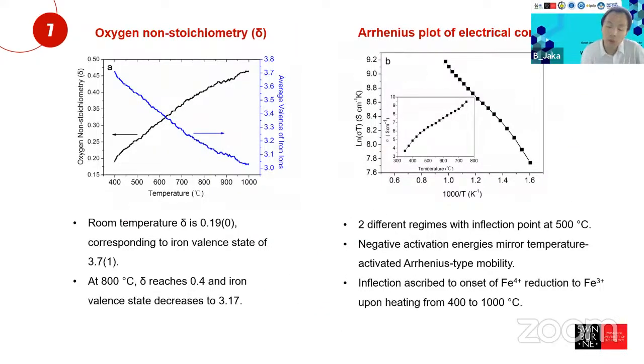So we need to check what the variation of this oxygen non-stoichiometry is at different temperatures. As we go from 400 to 1000, we can see that the oxygen non-stoichiometry increases from 0.2 to 0.45, and this is related to the reduction of the iron oxide in the perovskite lattice in the B site. So as the oxygen non-stoichiometry increases from 0.2 to 0.45, the oxidation state of the iron in the B site is reduced from 3.7 to 3.17.